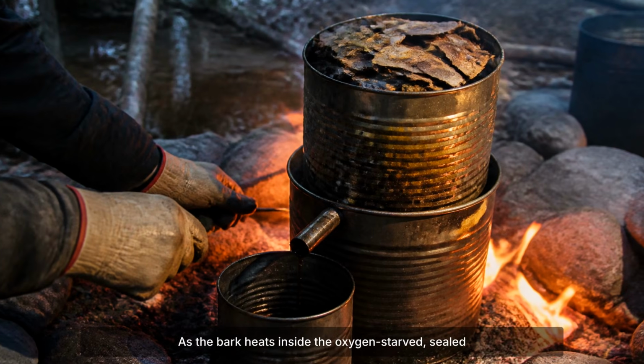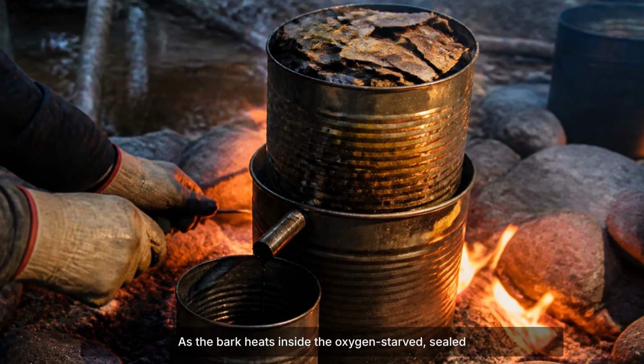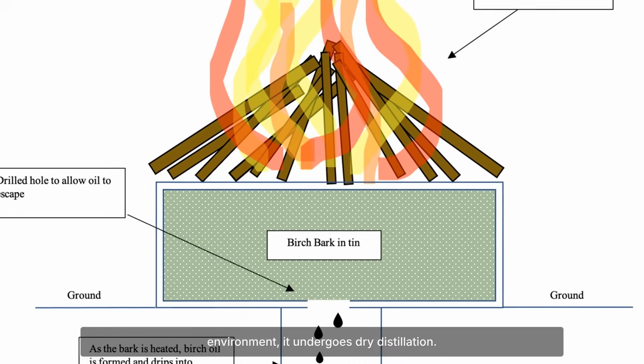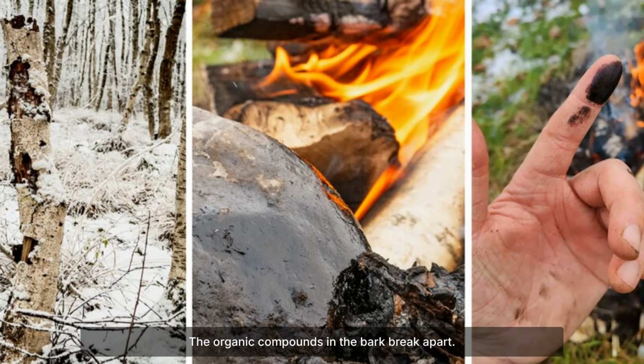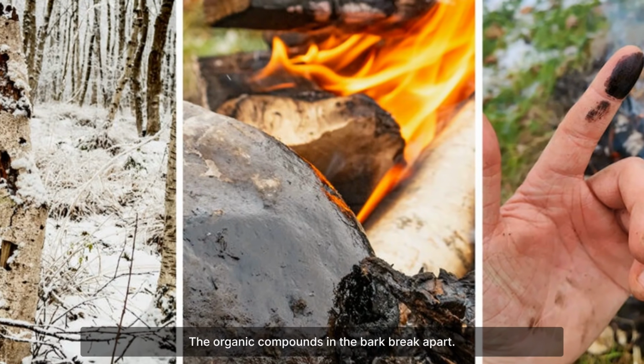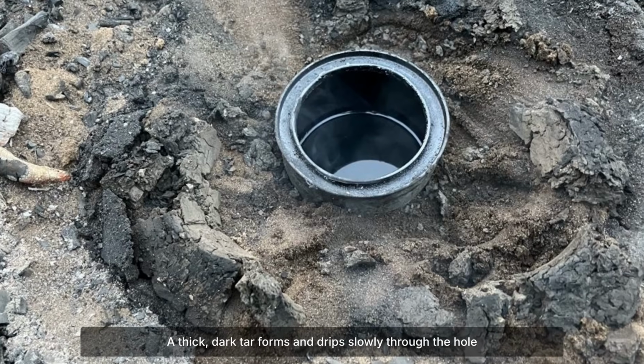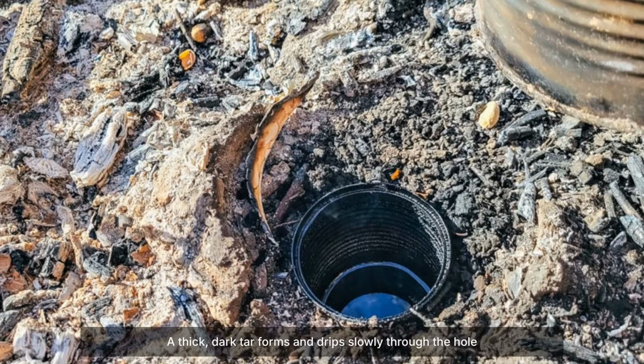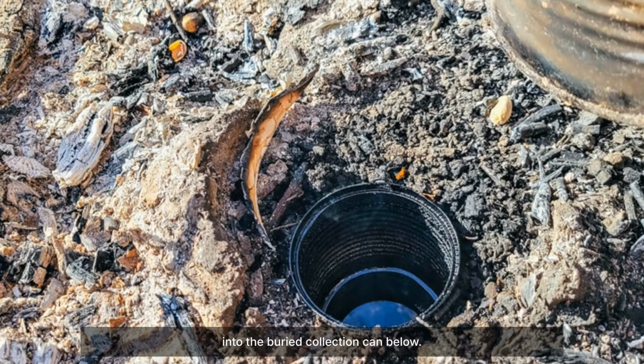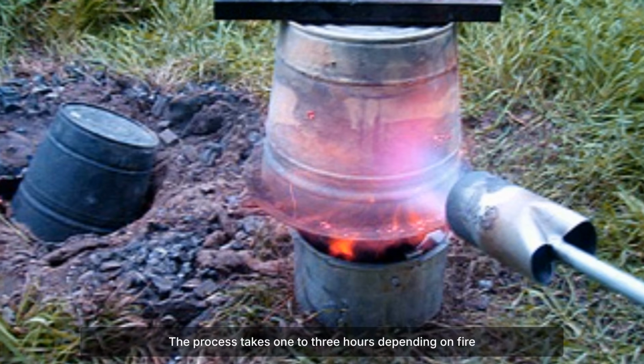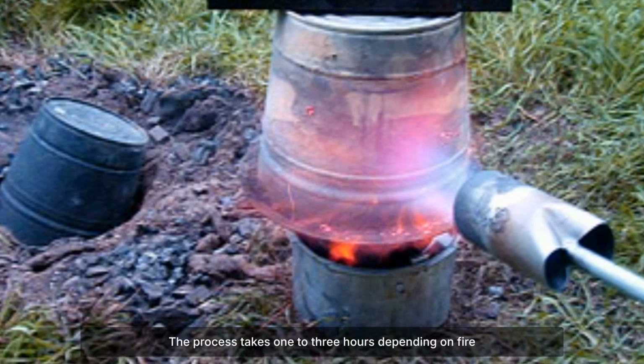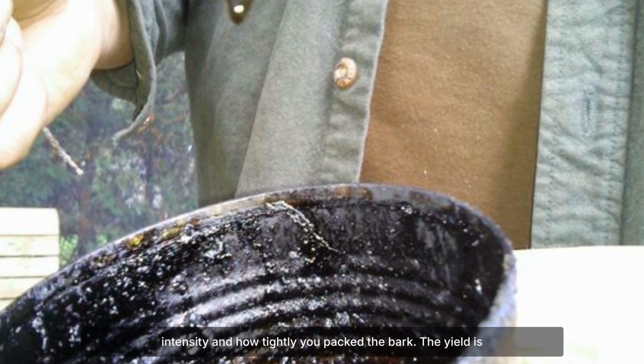As the bark heats inside the oxygen-starved, sealed environment, it undergoes dry distillation. The organic compounds in the bark break apart. A thick, dark tar forms and drips slowly through the hole into the buried collection can below. The process takes 1 to 3 hours depending on fire intensity and how tightly you pack the bark.